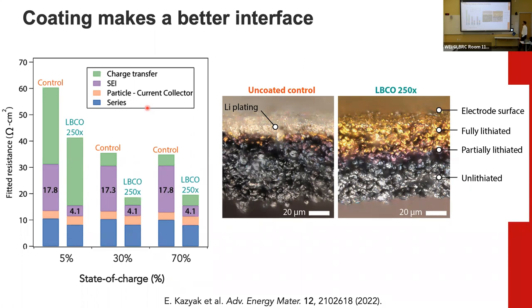And if we take apart the battery right in the middle of a fast charge, you can see that the control has lithium plating on the surface, which we're trying to prevent. And our LBCO, so this is an ALD, lithium borate, lithium carbonate material that we're putting on the surface, we just have gold graphite as we're going, and we're not plating lithium at all.